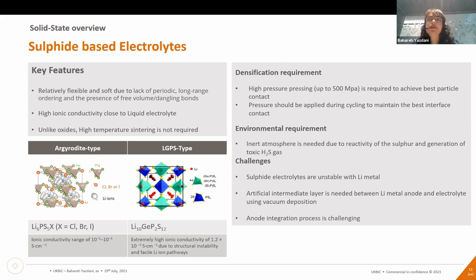So then an inert atmosphere is required, which can also be tackled by closing the manufacturing equipment in a closed space. But as I said, innovation is needed from the process side as well. Another issue is that, as I mentioned, some sulfides are not adaptable with lithium metal, but with some interlayer engineering, they can be adaptable. Artificial intermediate layers are needed. And of course, we also need to think about lithium metal anode handling during the process as well.